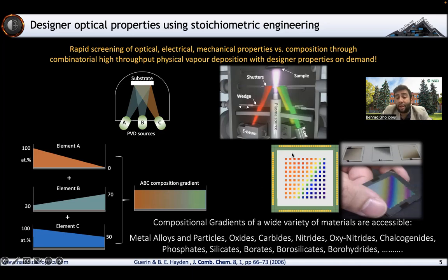And by just screening and characterizing this one sample, you can create a huge data set that allows you to very carefully pick the composition that's best for your application. Your application works at this particular wavelength range and needs these particular losses and these particular absorption levels. Here you go. You can very quickly point to the place on your sample, an alloy composition, that allows you to achieve your maximal operational metric. And this is a very universal technique. You can do it with various different material systems. It doesn't really discriminate against the material system. It's just a PVD technique with some spatial considerations. And through this, you can very quickly optimize your samples, your material system.